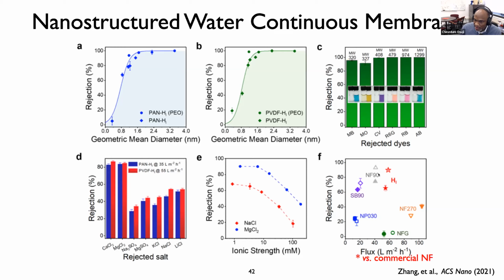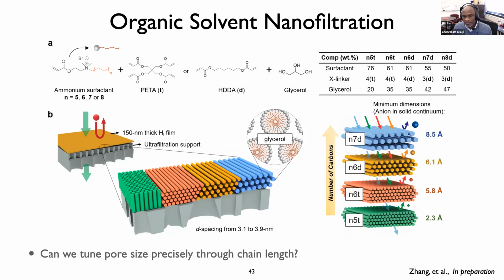And we found performance that is intermediate between what I would describe as two class-leading commercial nanofiltration membranes, namely Dow NF90 and NF270, which is a slightly looser thin film composite nanofiltration membrane. So they have attractive transport properties that rival and in some cases exceed commercial membranes, and they can be fabricated using scalable solution-based techniques. We've extended this recently to look at organic solvent nanofiltration in this same series of materials.